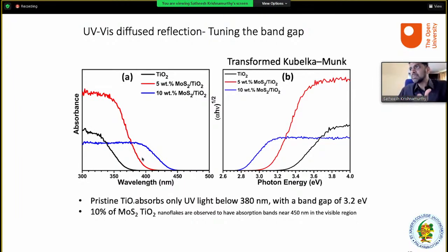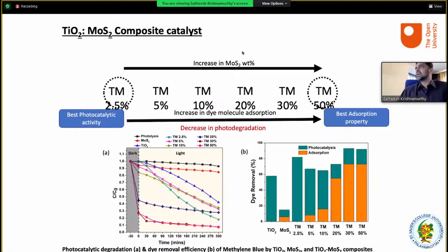Once you tune the band gap, then we started doping with different percentages from 2.5% to 50% of molybdenum sulfide. So we thought that 2.5% gives a really good photocatalytic activity, whereas 50% gives a lot of adsorption. So why can't we use a two-stage system? Here we get good absorption. And then this is the dark condition and the light condition. You can clearly see it's flattening out. Then we thought, why can't we use the same material for photo absorption and degradation?